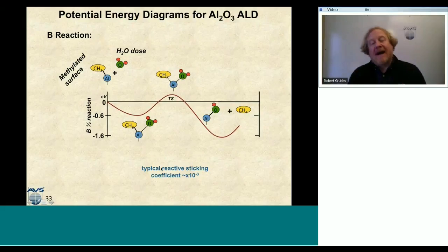So a typical reactive sticking coefficient for aluminum oxide is about 10 to the minus 3. So this is the potential energy diagram of how an ALD process actually takes place, and the numbers on the y-axis are pretty close to what they are in reality, according to simulations.